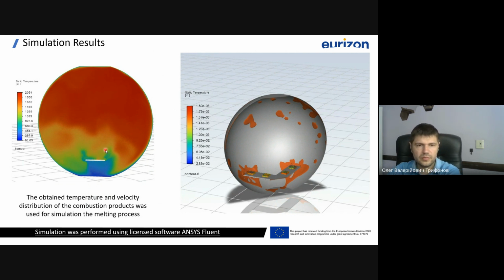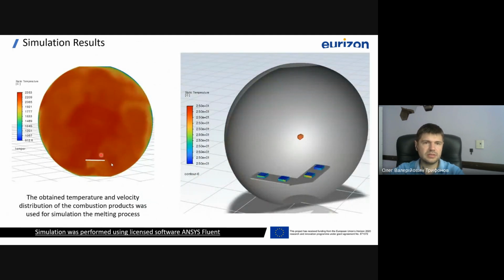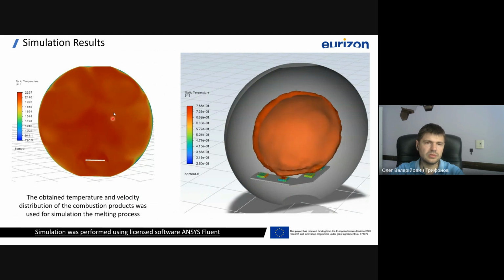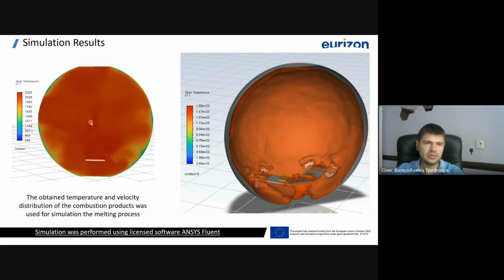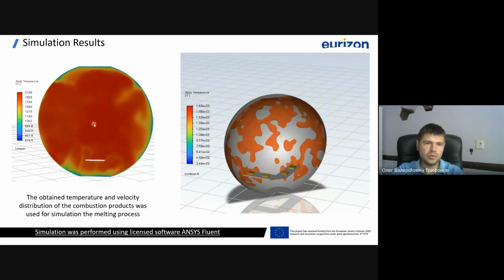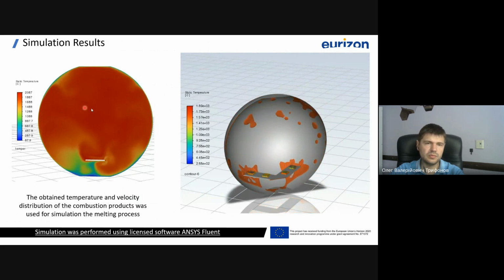And now we see that the temperature distribution is really nonuniform, and moreover we have a lot of flow fluctuations and turbulence inside the chamber after the combustion. And this flow field, of course, will influence the heat fluxes inside the part, and is very important for development of the simulation model.